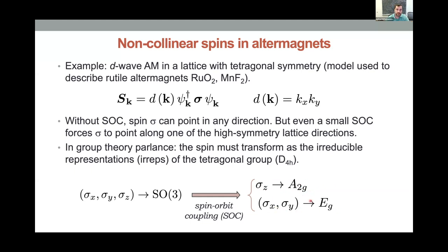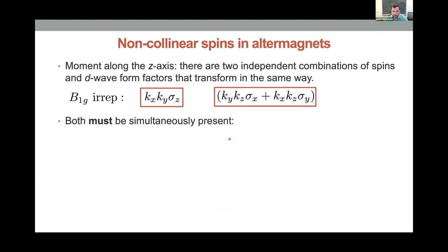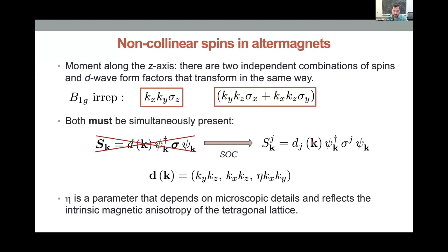What does it do? Well, let's assume that the spins point up, or z, okay? Now, this combination kx ky, this is a B2g times A2g, gives me a B1g representation. However, I can also write down other B1g representations by combining x and y spins, okay? So I'm just showing you here that this combination also transforms as B1g. And we know from symmetry that two objects that have the same transformation properties have to be simultaneously present. And that's why I mean that now you no longer think of this as a single spin direction with a d-wave component, but each spin direction has a different d-wave component, okay?